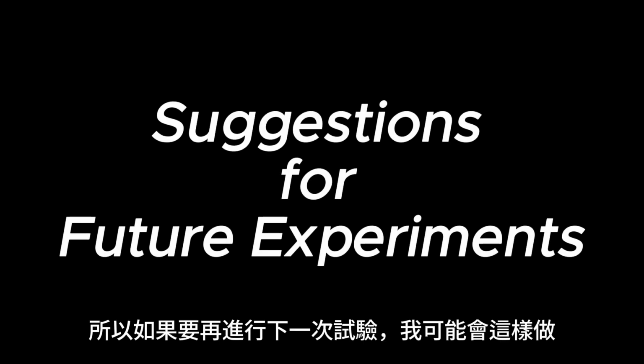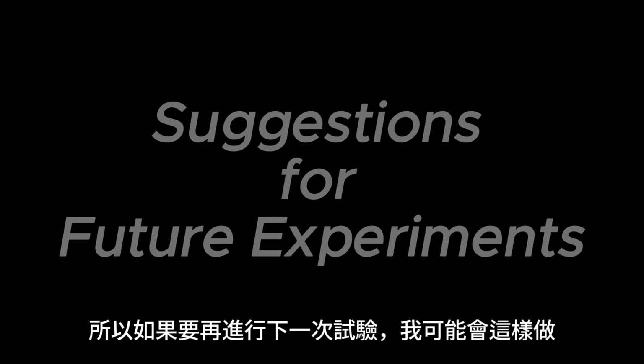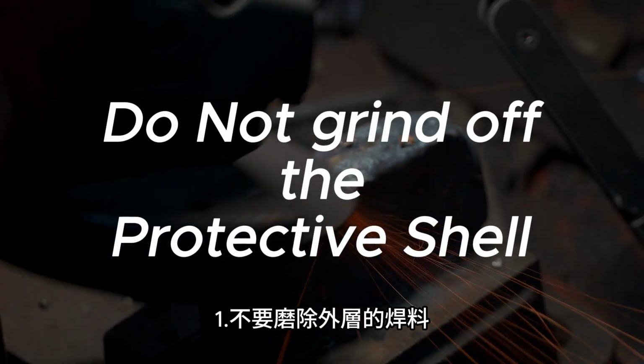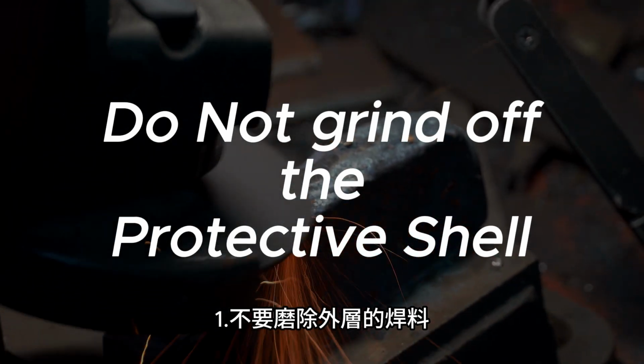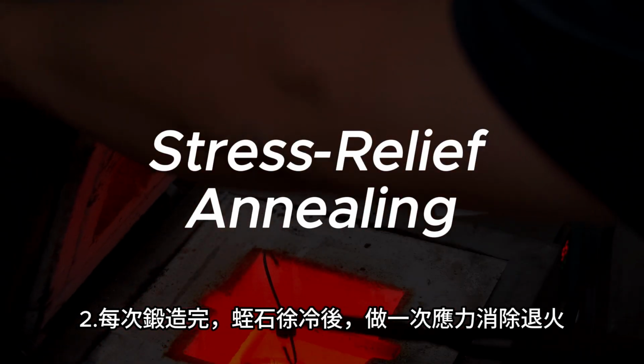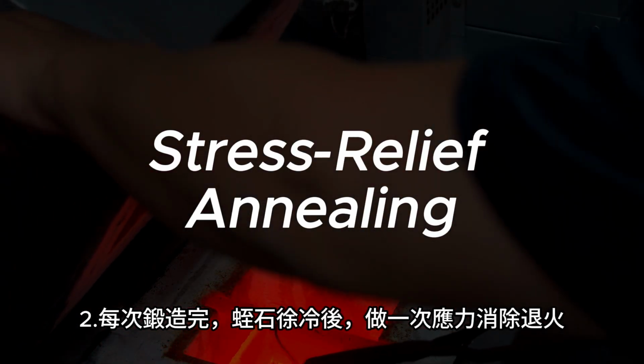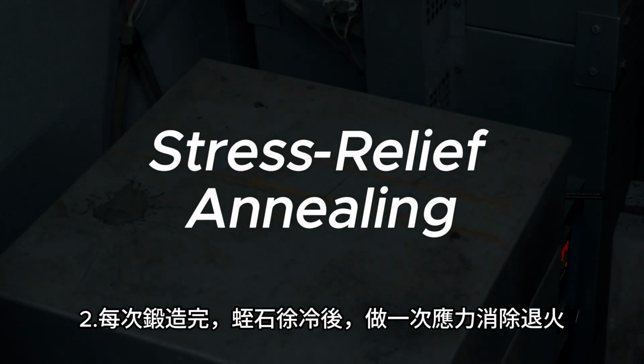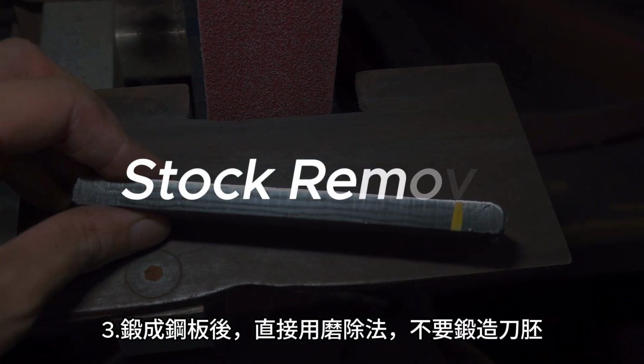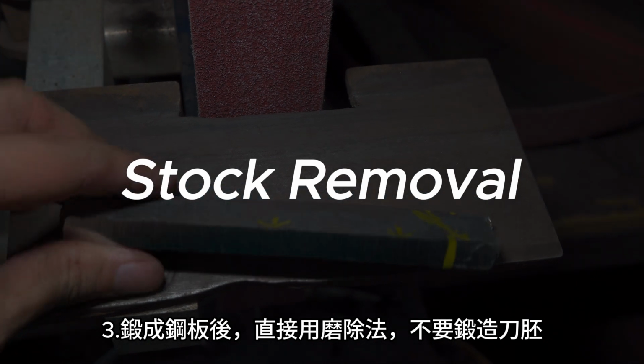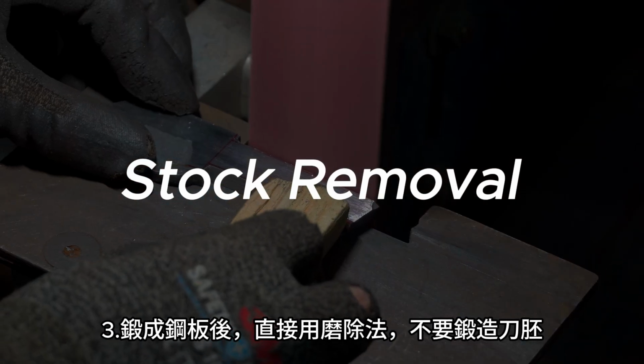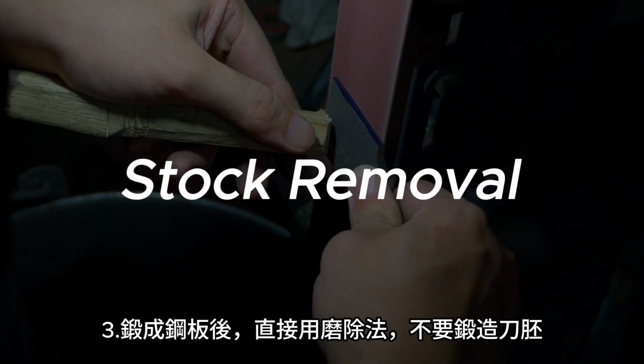So, if I'm going to conduct another experiment, I might proceed as follows. 1. Avoid grinding off the outer welding material. 2. After each forging, perform a stress relief annealing after slow cooling in vermiculite. 3. Once the steel is forged into a plate, use the stock removal method instead of forging the knife profile.